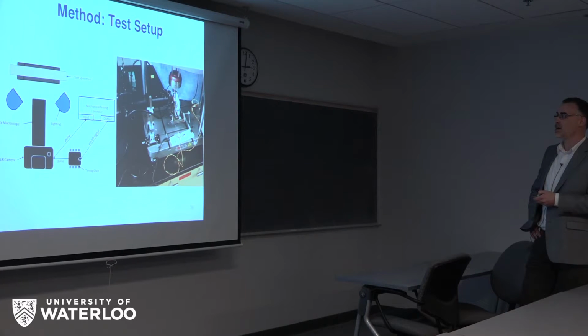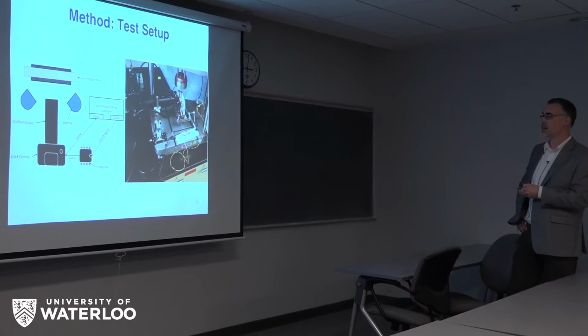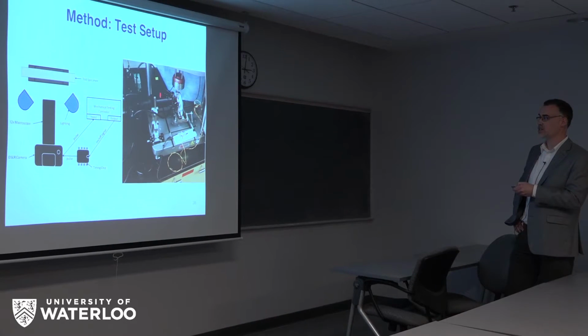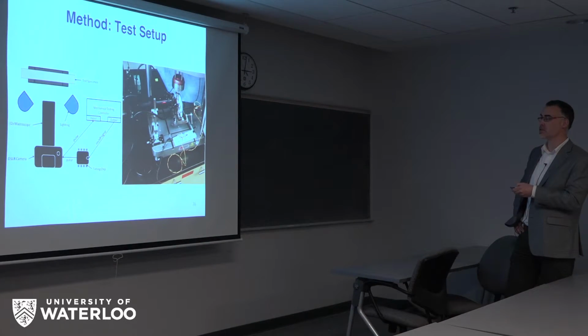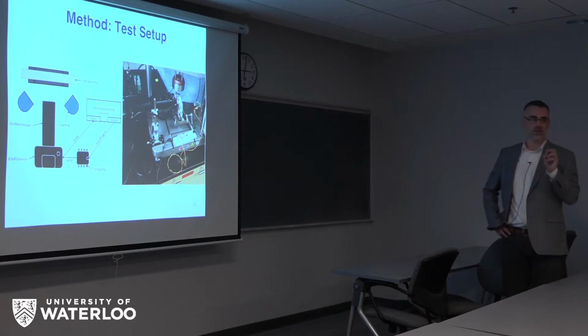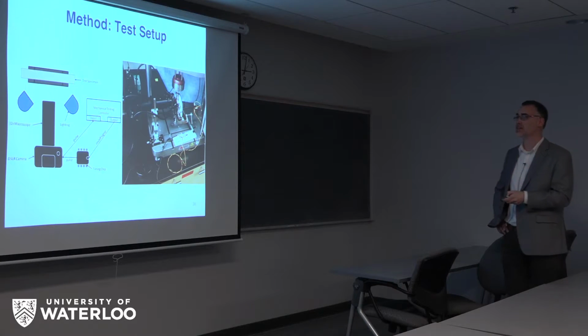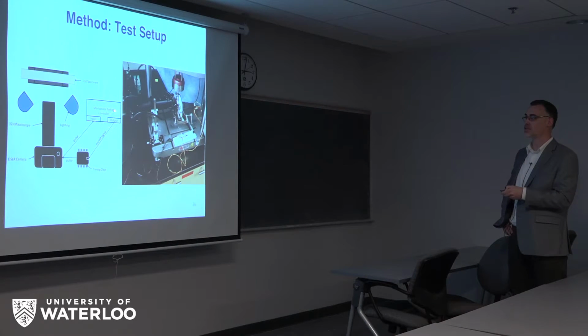So the test setup, we use an Instron benchtop, it's called an ElectroPuls E1000. And so we have our 3-point bending configuration in here with the load cell. And then all this contraption over here is a macroscope for 32 times magnification and a 25 megapixel digital camera in order to capture crack growth as the test is running. So we had a timing chip, which was triggered by the mechanical testing machine, and also the pulses were captured, so we knew the timing of the pictures, LED lighting, and then the digital macroscope capturing the specimen.